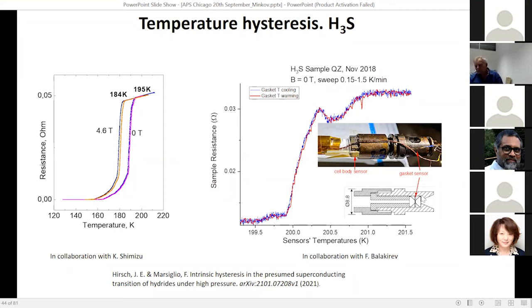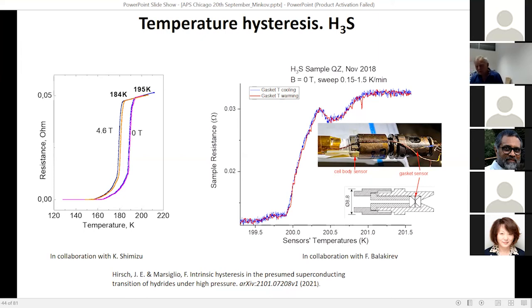This shows how the experiment should be done — but of course normally we don't have ideal conditions. In our routine method we cool down relatively quickly then warm slowly over about 10 hours, so the sample is in equilibrium with the cell and temperature sensor measurements are correct. We confirmed this also in Shimizu's lab — he obtained the same critical temperature as with our thermometer. One must be very careful and control measurements at every step.